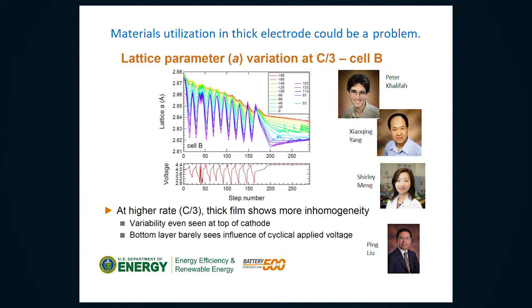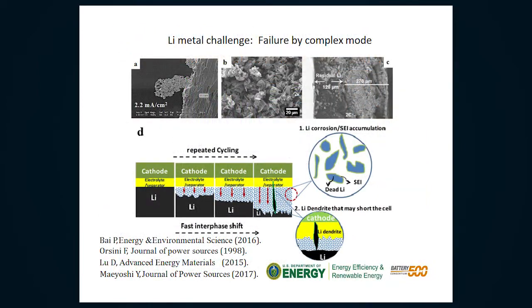Now what you find out really is this is the nominal charge discharge curve. And then you can look at the crystalline cell parameters from the top to the bottom. On the electrolyte side, from the top, you see this follows the charge discharge curve very nicely. But look at the bottom. The bottom is lagging behind, which means when you make very thick cathode material, even if you can make it not crack, it's difficult to utilize the whole electrode material at this kind of thickness. So we need to worry about that.